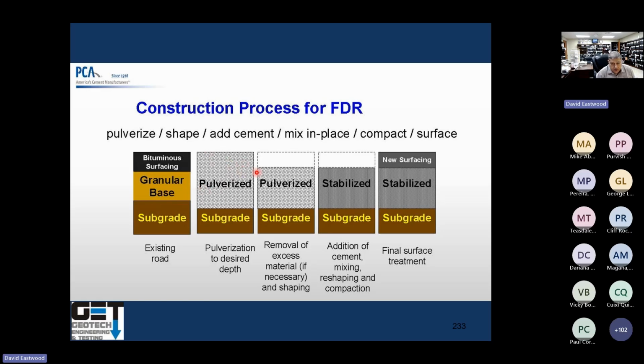That's the volume. Well, you're going to haul off some of it near the surface to allow for a surface course on top of it. Let's say 3 inches of asphalt. So you have to scrape off the top 3 inches. Then you pulverize the material with cement, and you stabilize it. This is your subgrade. This is your stabilized area. And then you put a new asphalt surface course on top of it. This is going to be your final construction.